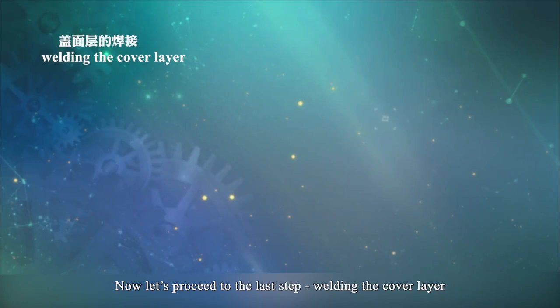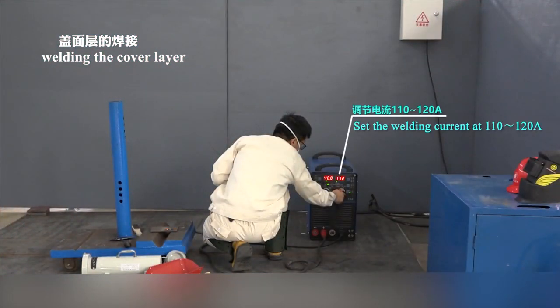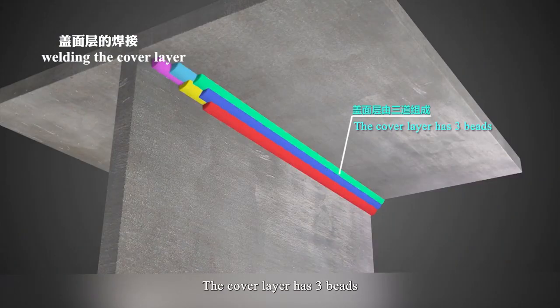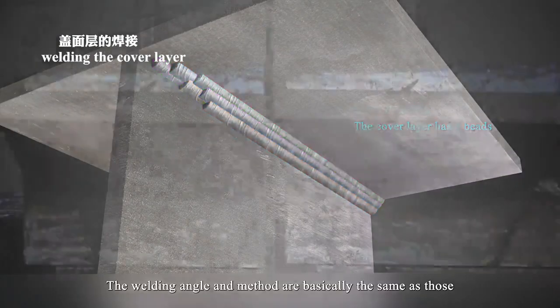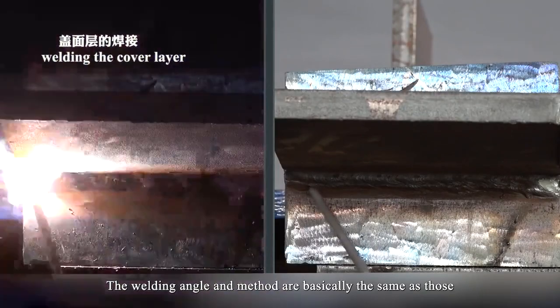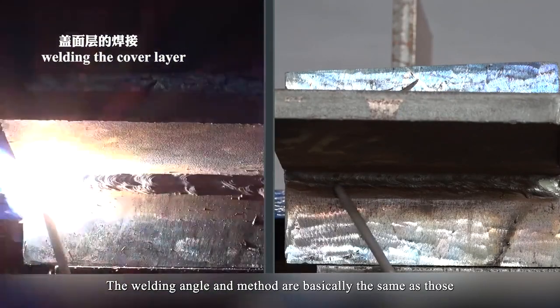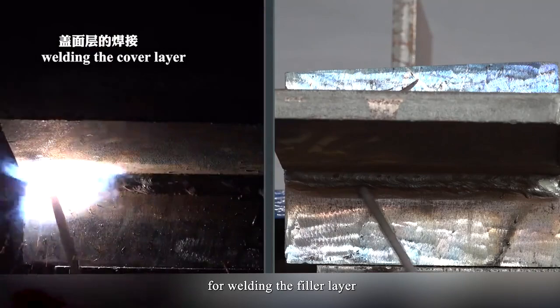Now, let's proceed to the last step, welding the cover layer. Set the welding current at 110 to 120 ampere. The cover layer has 3 beads. The welding angle and the method are basically the same as those for welding the filler layer.